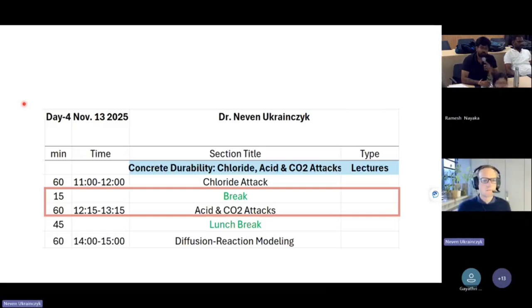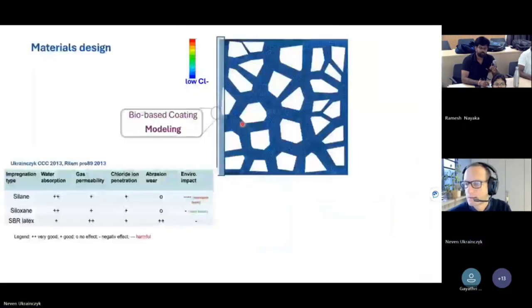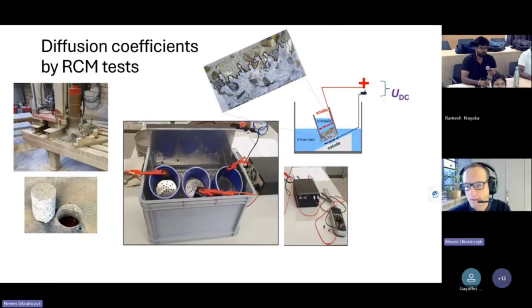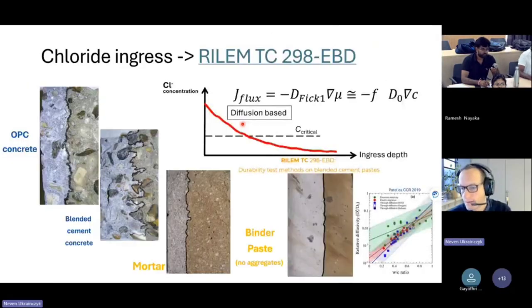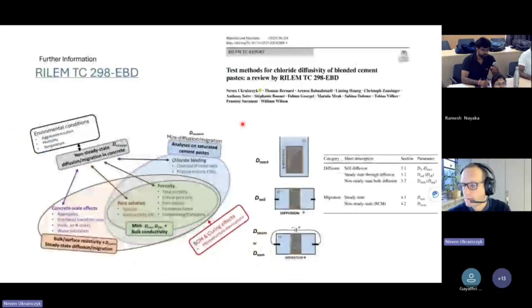I would always advise you to spray with silver nitrate and to really measure the penetration depth, because the current gives you only a rough estimation. It's better to really have the penetration depth. I would recommend you better to do the full RCM test, rapid chloride migration test, the NT Build norm. Yes, this is the worst method you can do, the rapid penetration. I know it's the fastest, but it's also the most uncertain.